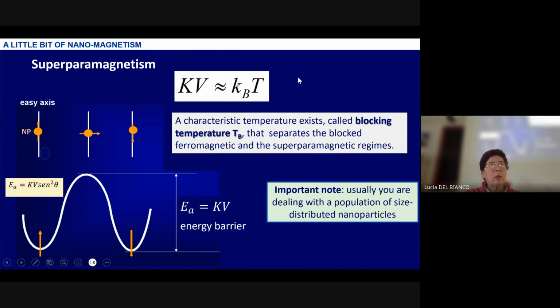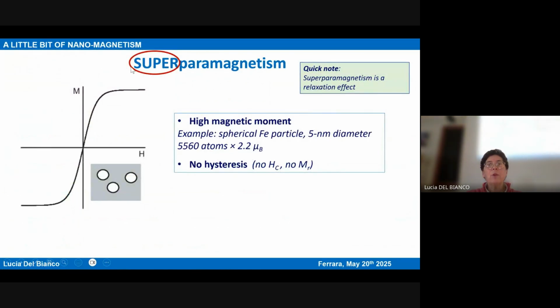So all this recalls what I've just said a few minutes ago about paramagnetism. But there are important differences between the two phenomena, which are really very different actually. But one difference is easy to understand. In the case of paramagnetism, what was flipping randomly was the magnetic moment of the atoms, okay? And here, what is flipping in all directions is the net magnetic moment of a whole nanoparticle, and therefore it's a high magnetic moment, and therefore we speak of superparamagnetism, okay? But as in paramagnetism, if you apply a strong field, you are able to magnetize all your assembly of nanoparticles, namely to align the magnetic moments in the field direction.